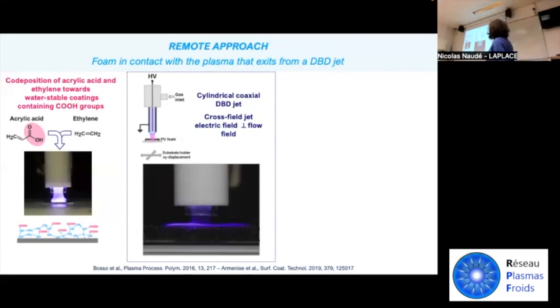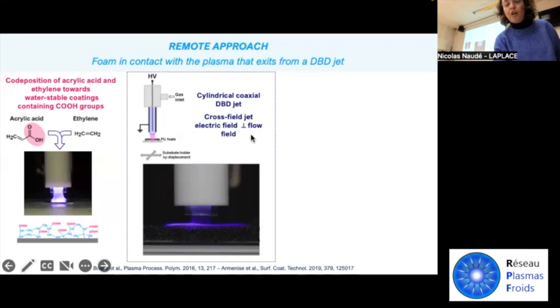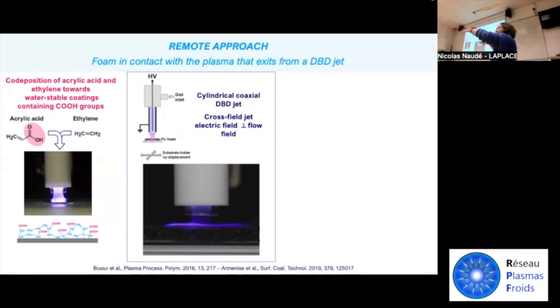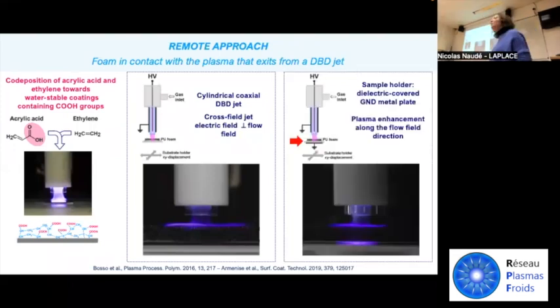So the first approach was to use, as you can see in the scheme of the source, a simple cylindrical coaxial DBD system, in which this is a cross-field jet, in which the electric field is perpendicular to the flow field. With this configuration, we just observe the spreading of the plasma plume over the top surface of the foam sample. You can obtain some deposition inside, but it's not so effective. For some applications, that can be interesting, but we would like to improve the deposition inside.